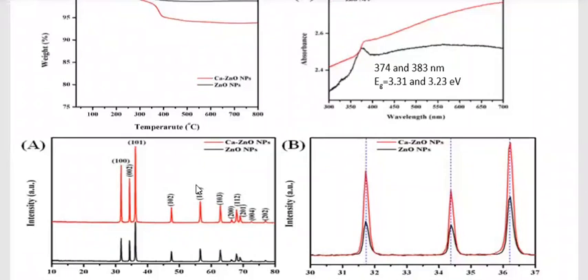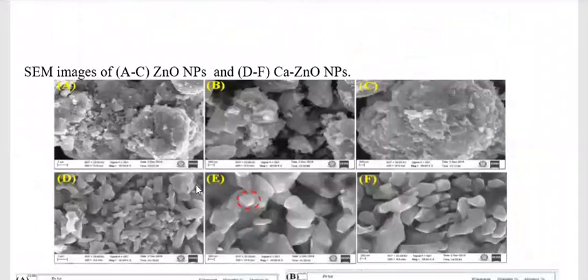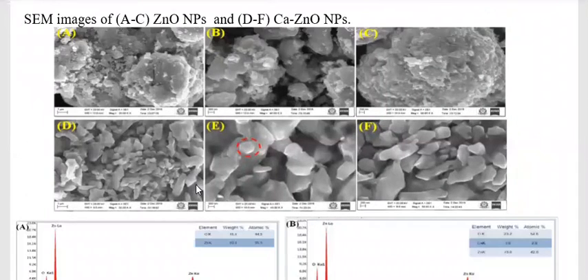The same images also show the zinc oxide nanoparticles have spherical morphology. The calcium doped zinc oxide nanoparticles look like ball-like structures, as confirmed by the EDAX spectrum. The first one is zinc and oxygen, the second one is zinc, calcium and oxygen. This shows the elemental analysis, weight percentage or atomic percentage.